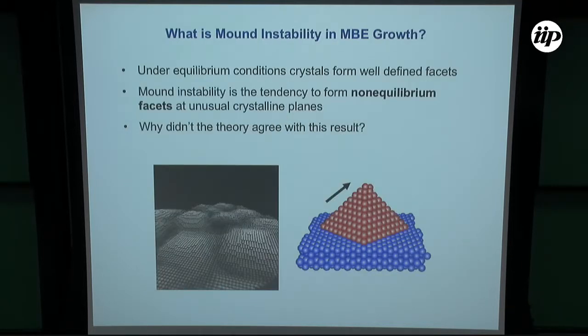These mounds are reminiscent of equilibrium facets, right? You know that under equilibrium conditions, crystals have a faceted surface. These facets are 1,0,1, 1,1,1, those kinds of facets that people study in equilibrium crystals. But here, what we observe are facets, but these are non-equilibrium facets. So we don't really understand how you can have them. In equilibrium crystals there's a detailed balance between addition and desorption, and that's why you get the facets. But where does that come from here? Because these are actually facets, but they are non-equilibrium facets.